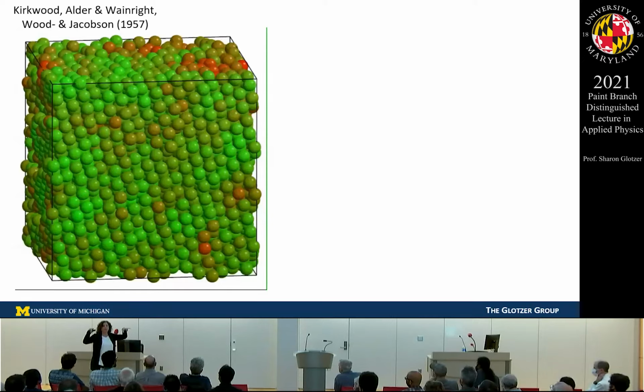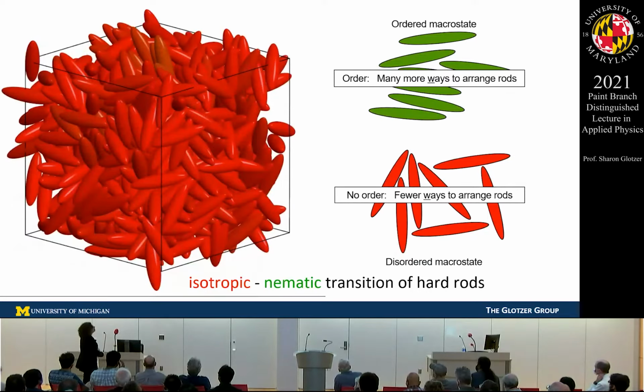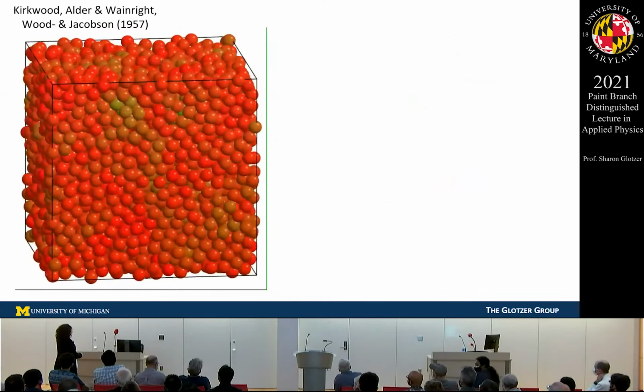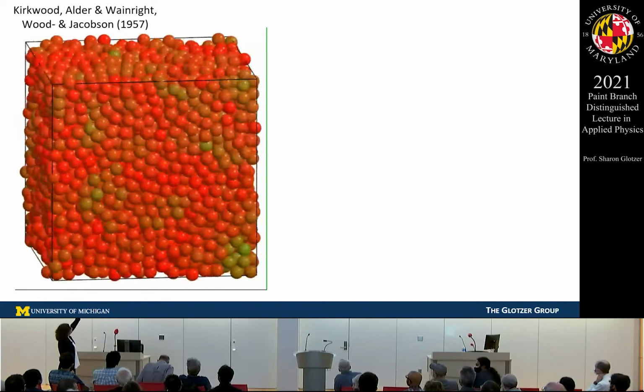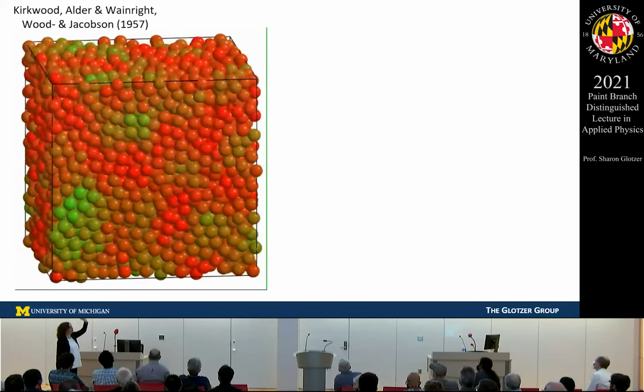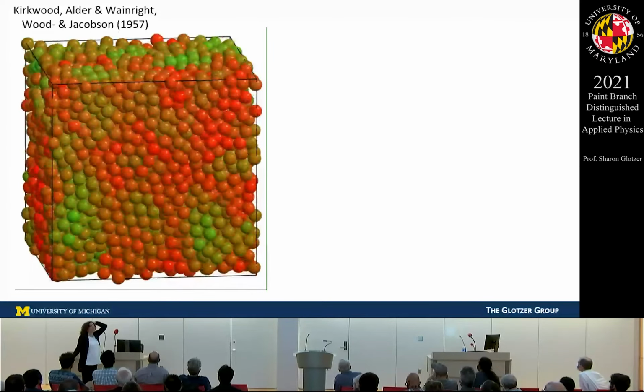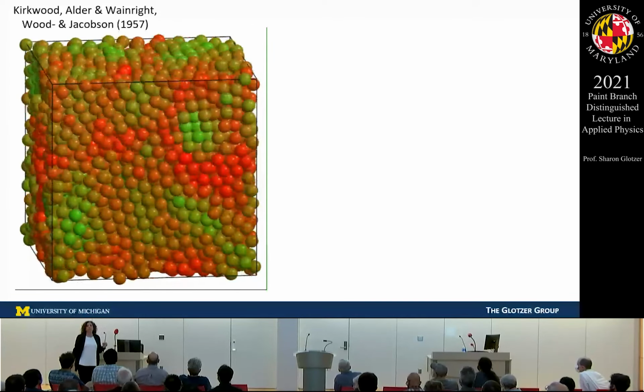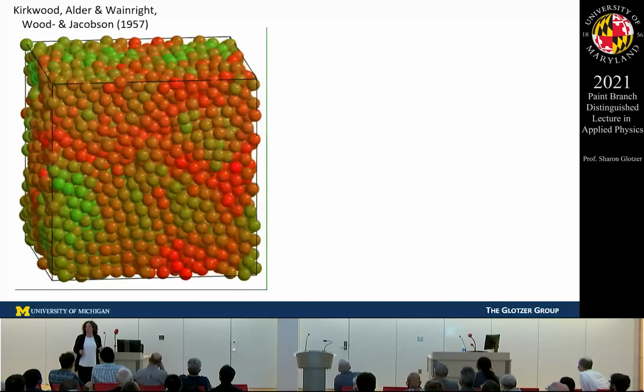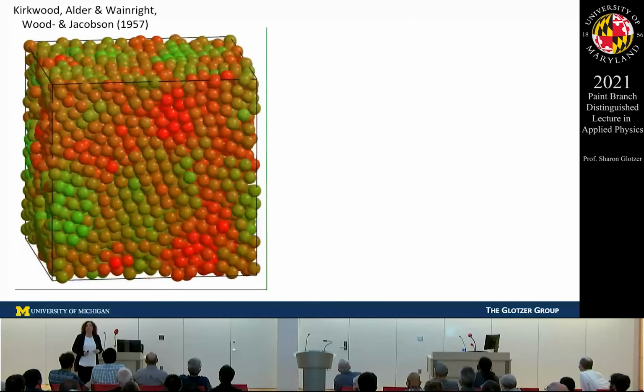And Wood and Jacobson did a Monte Carlo simulation, basically the same thing that I've been showing you. It took them a year on a Cray at the time, which is cool, for 500 particles. So here is a bunch of spheres at a packing fraction, or particle volume fraction, of about 52%. Green means that locally it's organized with its neighbors, in some kind of local ordered configuration.